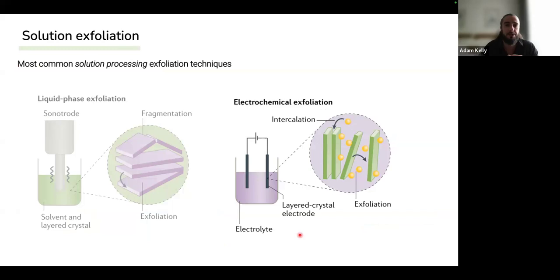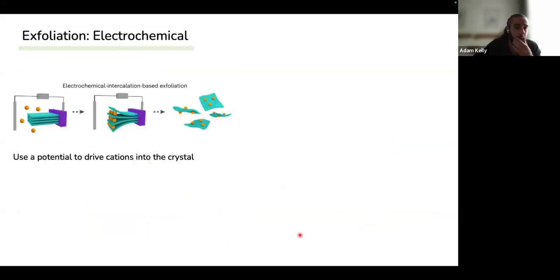Now, the other technique that I mentioned is electrochemical exfoliation. So this works by taking a crystal itself, you attach it to an electrode, and then you have a counter electrode, which is something like platinum or graphite. And then you apply a potential to your crystal, and you use this to drive ions in between. What this does is that it widens the intersheet layer in between the nanosheets. And then when you apply just bath sonication for a few minutes, because these layers are now electronically decoupled, they will very easily exfoliate inside of a material.